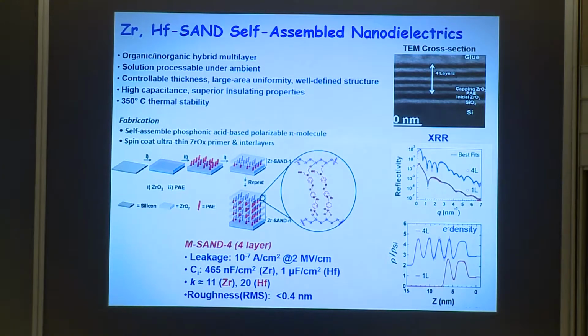Here's the X-ray reflectivity. And so this is the 4-layer. And the data points, the fit is right on top of the data points. Here's 1 layer. So it's the diffraction. And of course, the zirconia or hafnia is doing most of the scattering. You can do the Fourier transform of the X-ray reflectivity, and you can see the different layers. So here's 4 layers. Here's 1. Leakage is small. The K for the hafnia material is roughly 20. So that's very, very large.